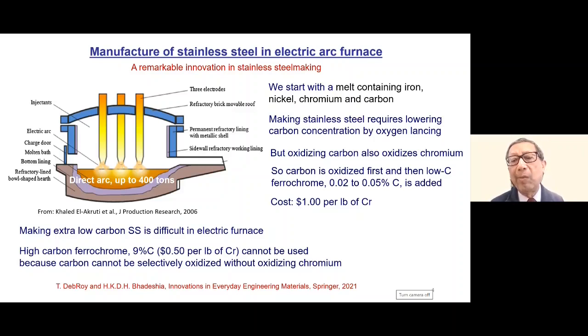Ferrochrome costs about $1 a pound, low carbon variety. We cannot use the high carbon variety of ferrochrome that costs much lower, 50 cents per pound of chromium, because if we add higher carbon containing material and we try to oxidize that, we will oxidize chromium as well. So selective oxidation of carbon is not possible in electric furnace.